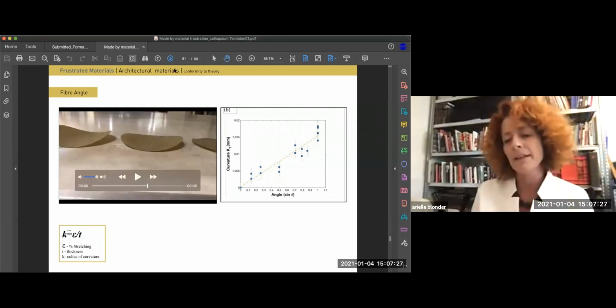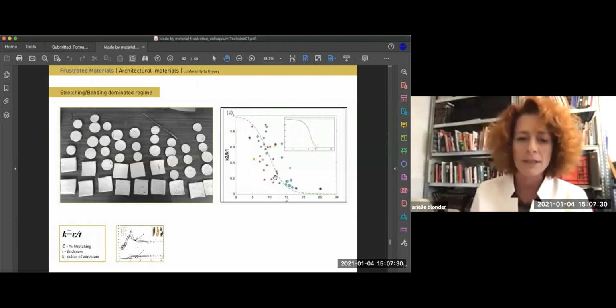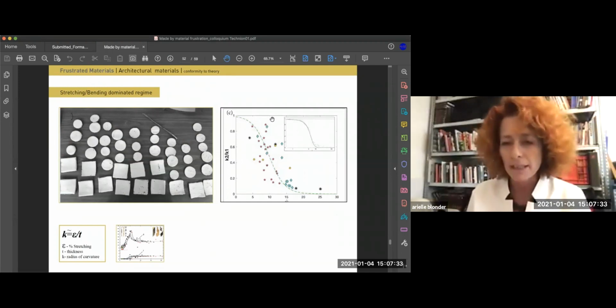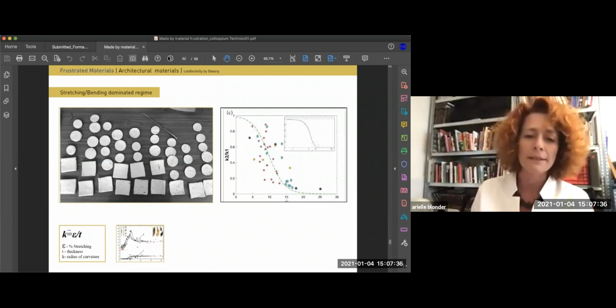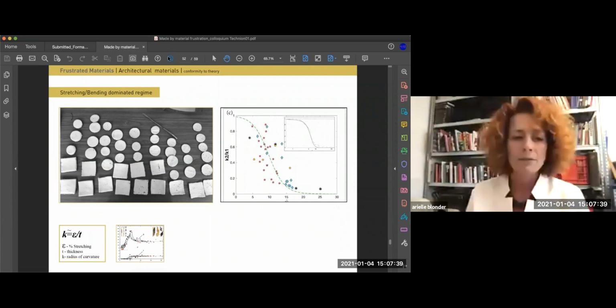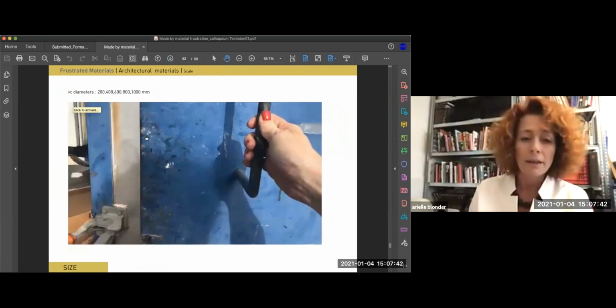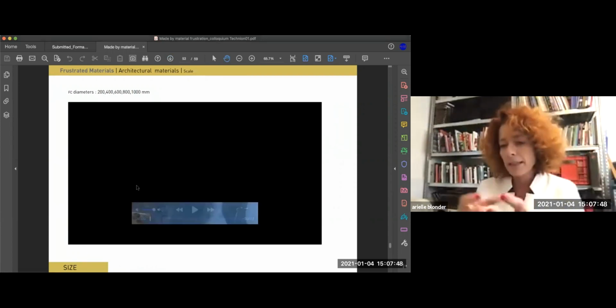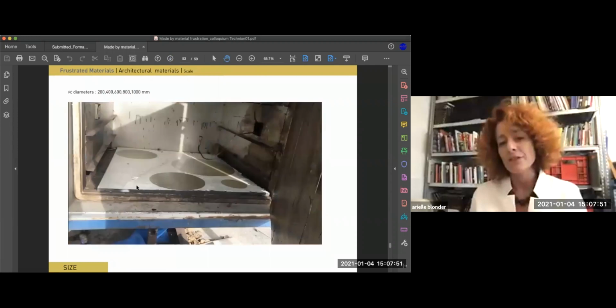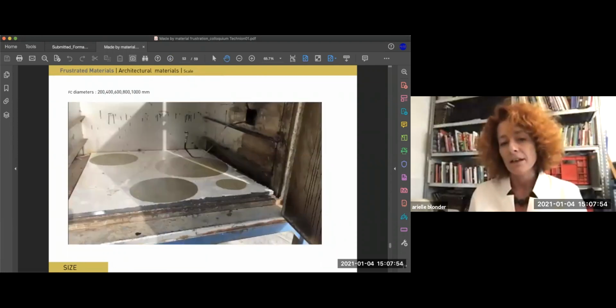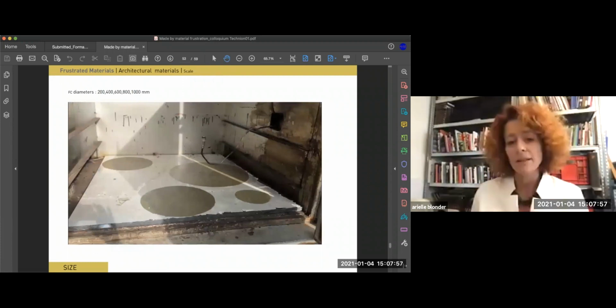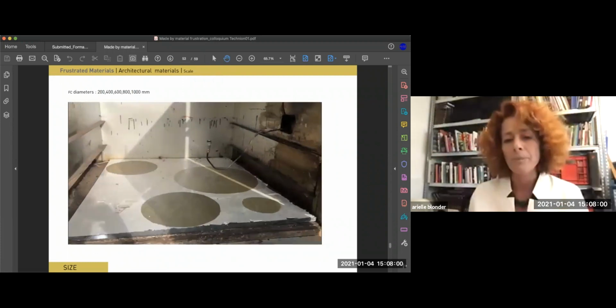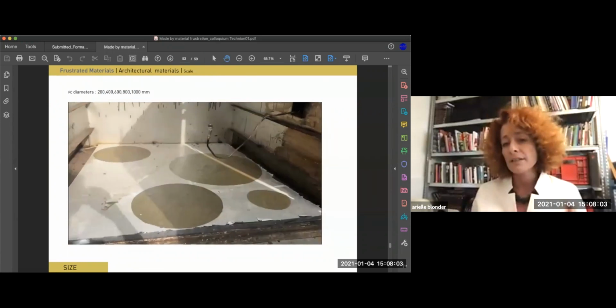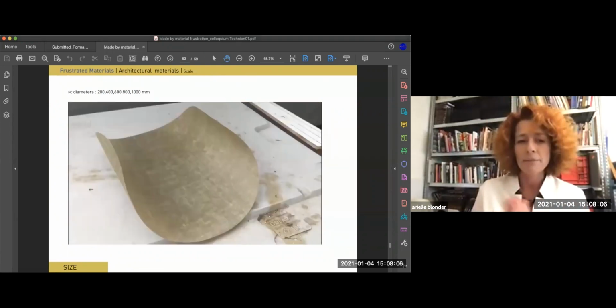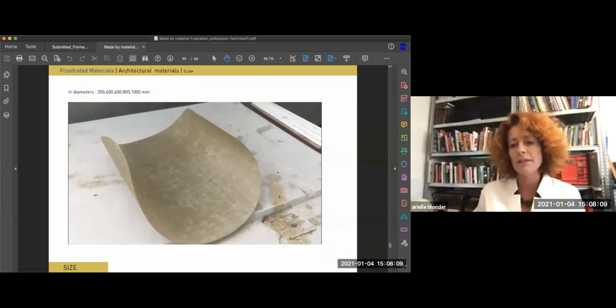And finally, the bending dominated or stretching dominated regimes. Here we have the ceramic materials that are actually behaving like the curves that we were expecting. So some of them would be bending dominated and some stretching dominated. So we were saying material, and now comes scale, because we cannot remain in our samples. So this is the first test to see the effect of scaling over the elements. You see discs here that are ranging between 20 centimeters and a meter. You see the elements are curling up.